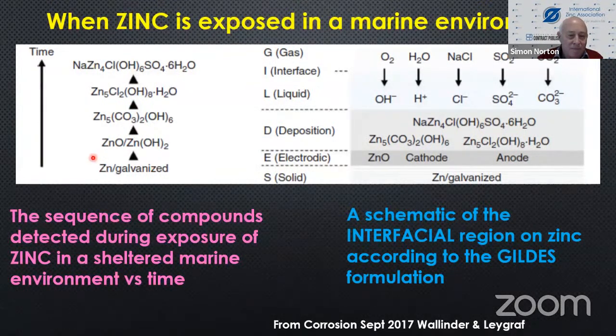or thermal spray. Well, it first forms zinc oxide and zinc hydroxide. Then it reacts with the carbon dioxide in the atmosphere to form zinc carbonate hydroxide and with the oxygen in the atmosphere. Then, because it's at the sea and there's salt spray, it reacts with the chlorides, and you then get zinc chloride hydroxide in this quite complex molecule. And then finally, the sodium gets involved, the zinc is involved, the chlorides, and even some sulfates from the sea. And you get this over time. This is what you get when you expose zinc to the atmosphere at the sea.